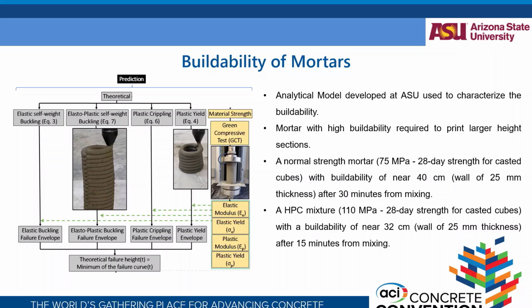The buildability for these 2 mixes was checked on a 25 mm thick wall, because right now we're going to print walls. The buildability from prediction and experiment were close, around 40 for the normal strength mix at 30 minutes from mixing, while for the high performance concrete, it was about 32 centimeters at 15 minutes after mixing.